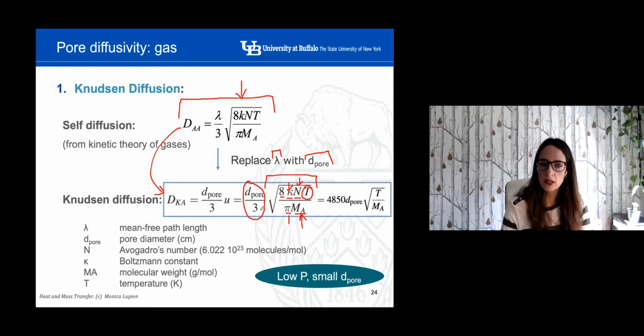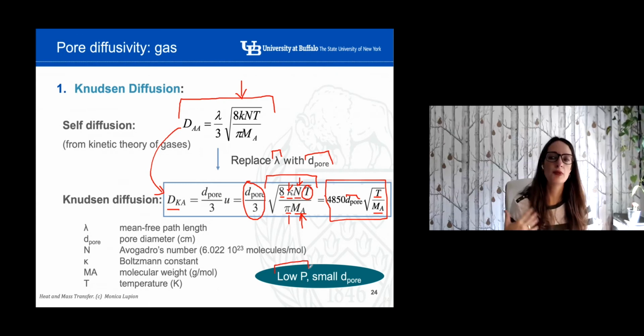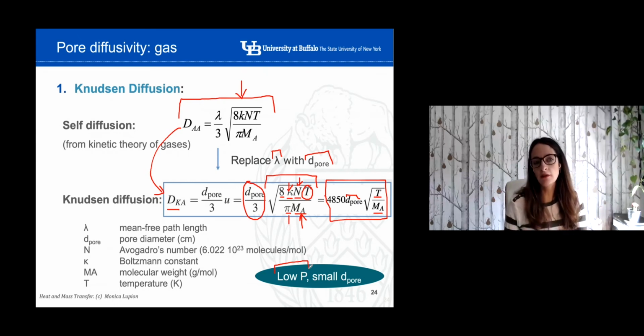So if you group all the different constants, we can say that the Knudsen diffusion is equal to 4,850 times the diameter of the pore, times the square root of the temperature over the molecular weight of the element. This equation is usually applied when we have, as I mentioned, a very small pore diameter. Otherwise, if the pore is sufficiently large, we won't see the Knudsen effect. Also it applies at low pressure, because when the pressure is elevated, the particle will go through the pore without many interactions, and therefore the Knudsen diffusion will not be that significant.